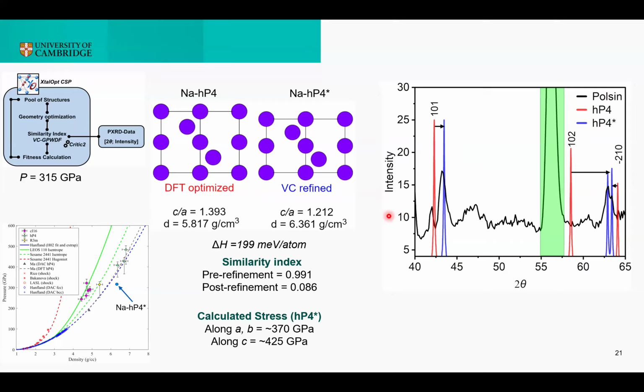Now it's very hard to claim that this is exactly the structure that was observed experimentally. But I think that it is very interesting that without any information about a powder X-ray diffraction pattern, a distorted sodium HP4, which is the thermodynamically most stable structure, was still found as the best candidate at these pressure and temperature conditions. Nonetheless, I want to highlight that this method finally enables the exploration of distorted structures, especially at extreme conditions, which would otherwise be precluded with standard DFT or molecular dynamics simulations.